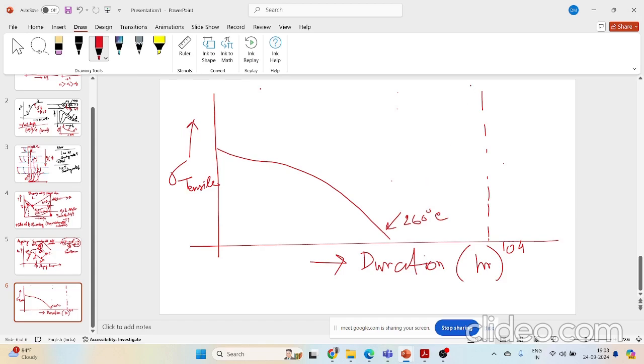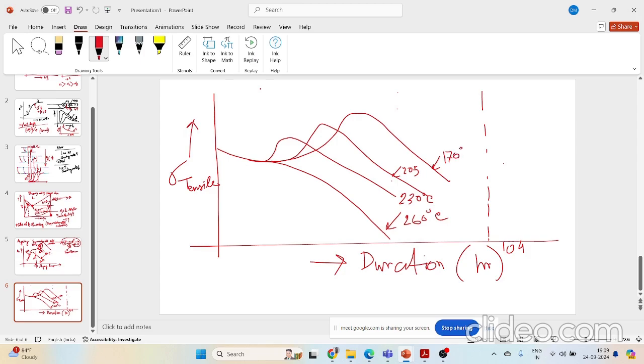So this was aged at 260 degrees C. And as you decrease your temperature, it will vary something like this. So this was somewhere around 230. This was somewhere around 205. This was somewhere around 170 and so on, right?